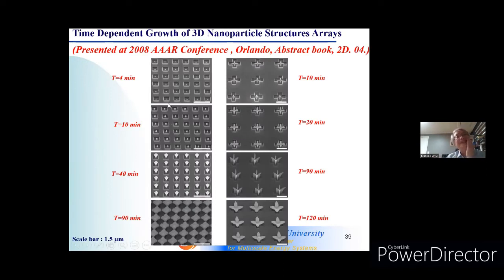We presented this in the 2008 AAAR conference. At 4 minutes, particles only deposit at the center region. At 10 minutes, they grow upward. At 40 minutes, they grow beyond the PR height. At 90 minutes, they interact with other structures to become this kind of three-dimensional nanostructure.